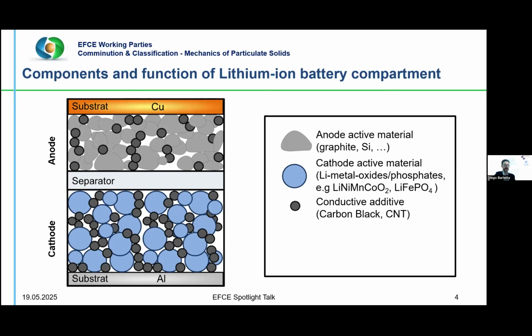Now, conductive additives are also incorporated to enhance the electrical conductivity within the electrodes. Carbon black forms a conductive network consisting of spherical aggregates with primary particle size ranging from 10 to 500 nanometers. Carbon nanotubes, one-dimensional nanomaterials with diameters of 0.5 to 80 nanometers and lengths of 5 to 20 micrometers, provide efficient electron transport pathways.